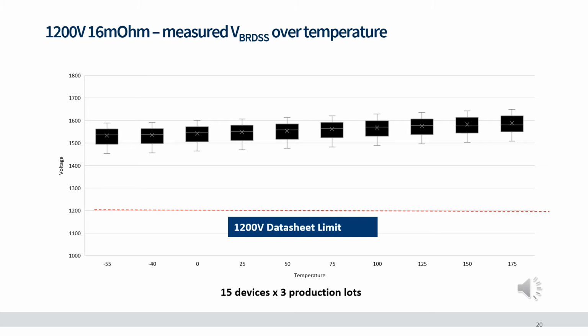As you can see, this margin could be significant, and this contributes to why our SiC MOSFETs have proven to be very robust to overvoltages. This margin doesn't mean that we recommend our customers to operate above the specified breakdown voltage value, but we do want to make them aware of this feature. In the lifetime of a power conversion system, there could be unforeseen situations where a high overvoltage event occurs. For an IGBT, this could very likely cause a failure. For our SiC MOSFETs, they would just continue to operate.